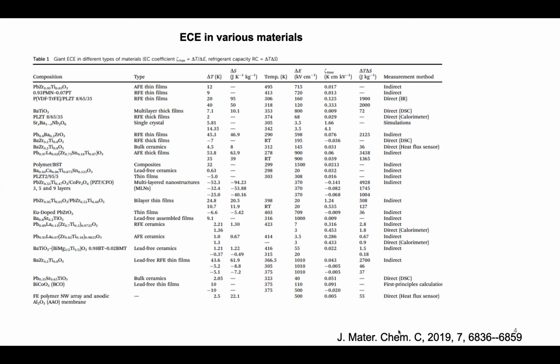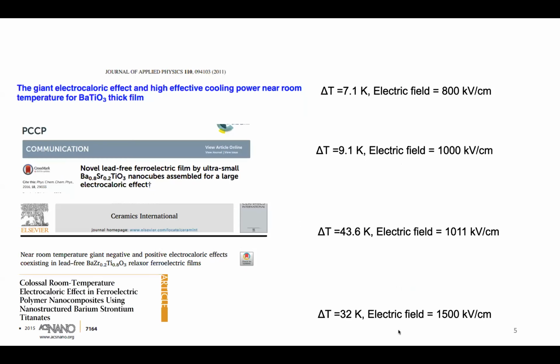However, we are interested in the lead-free system, that is the BZT system. In these systems also, you can see people have already tried it from the experimental side. A large change in the temperature is observed, up to 43.6 Kelvin. Of course, reproducibility is a big issue in these works, and we wanted to address that part also in our work. And you can see the field here; they went up to 1,500 kV/cm.